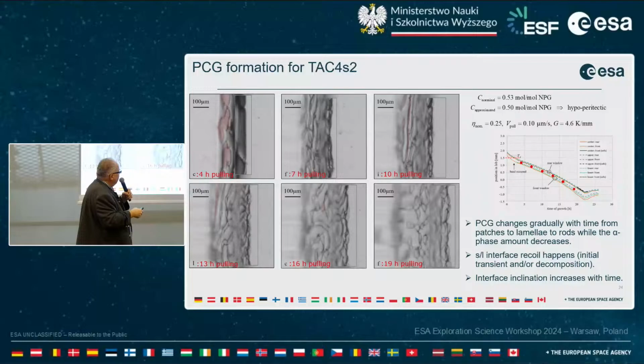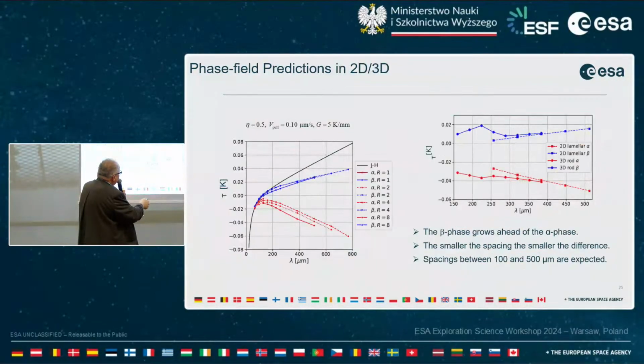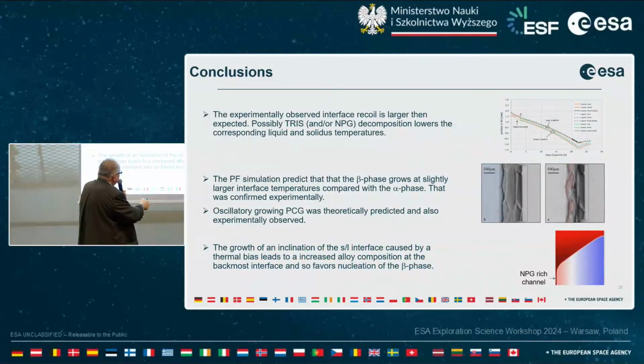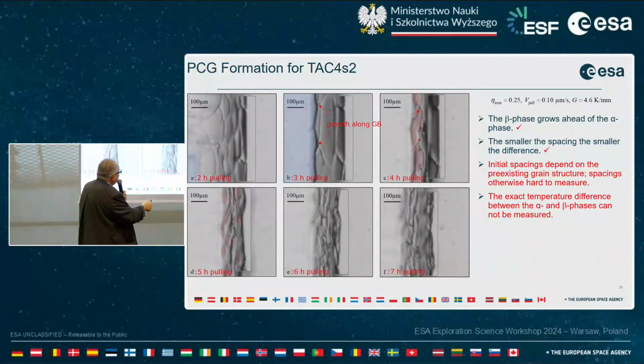Okay, so, and see, yeah, what we found out. We found the same one, but in one sample and over the time. We start here like this is more or less like a zigzag structure, as I showed you before from the phase field simulation, and over the time you can see here after 19 hours more from these patches we have more or less such small rods.